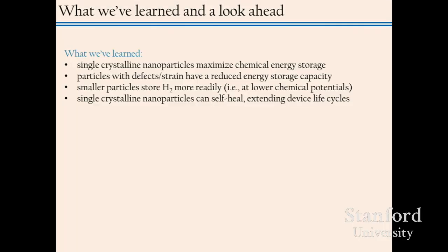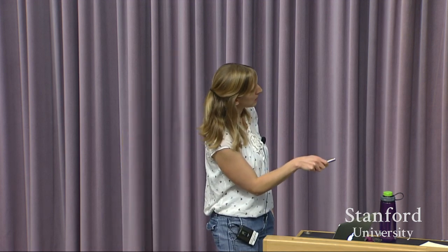Okay, so what we've learned, basically single crystalline nanoparticles, regardless of shape, can maximize chemical energy storage. Basically, you can get the particle to fully transform, and if you have smaller nanoparticles, you can get that to happen at smaller chemical potentials. So smaller particles store hydrogen more readily, i.e. at lower hydrogen pressures. Particles with defects or strain, such as the icosahedra, tend to have a reduced energy storage capacity. So essentially, we're not able to get any ions into the core of those compressively strained nanoparticles.